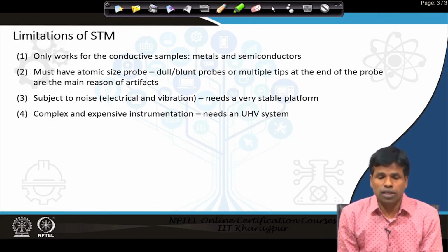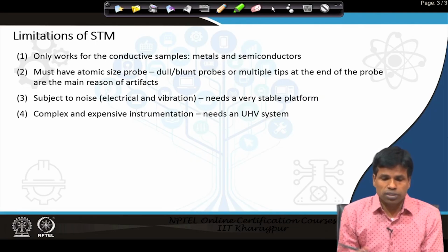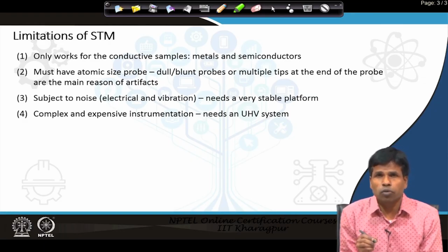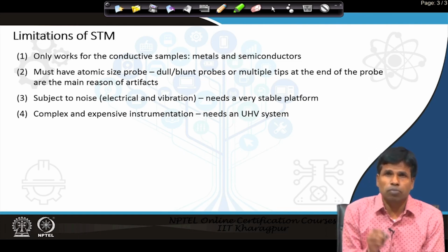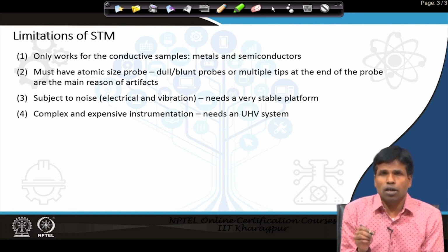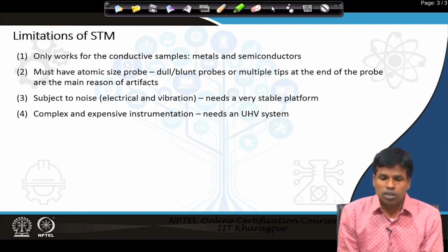In particular, this is the tunneling current, and we use an atomically sharp tip, because we get information at the atomic scale. The tip should have a single atom, then only can we get the current passing between two atoms, one atom in the sample and one atom in the tip. If our tip is dull or blunt or has a larger size, then our lateral resolution will also degrade, or the image can have artifacts. So, a dull probe or multiple tips would become a problem for the scanning tunneling microscope.